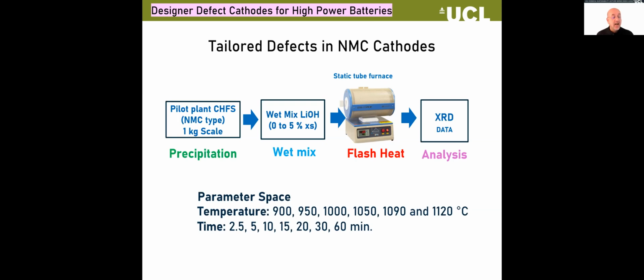And I started thinking, because we had this other project looking at flash heating for the LLZO, about whether there was any way we could actually make cathodes in flash, with a short heat treatment time, even though everything in the literature tells you that's a bad idea. And the reason is, in solid state electrolytes, it's okay to have a defective solid state electrolyte because that's how lithium ion diffusion works well when you've got a very defective structure. But in cathodes, the general consensus is it's a layered material. You don't want to have certain types of defects in there, because they block lithium ion diffusion. And it's generally considered a really bad idea. Well, actually, it turns out that's not true, thankfully for me.